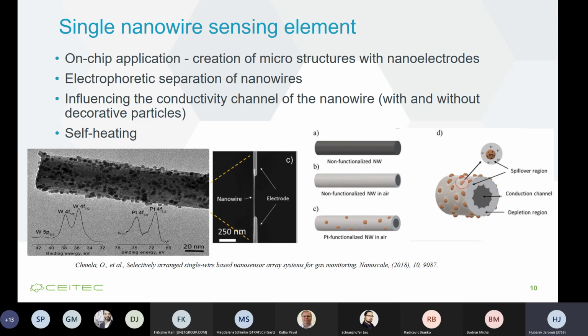chemoresistive sensing elements. But the advantage of this device or single nanowires is it's self-heating, because if you apply any measurement current, the nanowire heats up during the measurement. So it can be advantageously used for heating to the operating temperature. And you can imagine that the power consumption will be very, very low in comparison with standard devices. So it will be in microwatts, not milliwatts, as in the standard case. So these are some results, not so old.